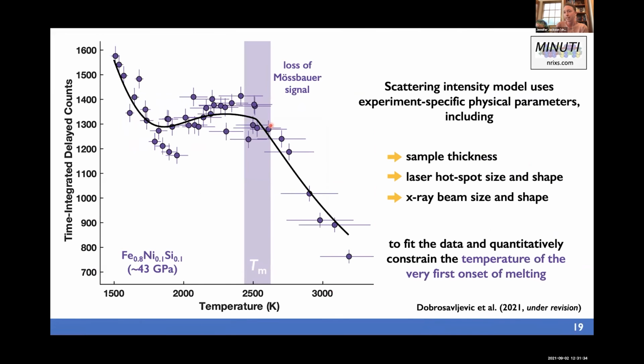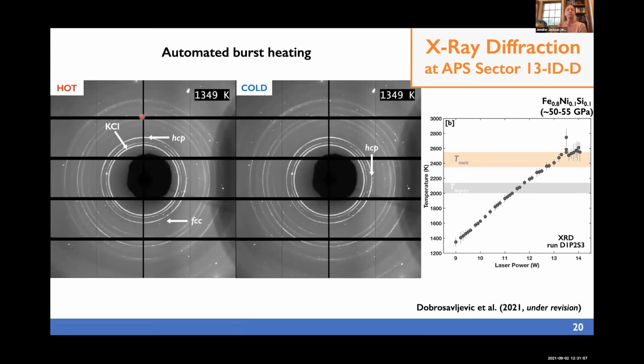The important thing to mention is that the determination of the melting point uses experiment-specific properties. So we use a physical model to describe the scattering process as well as a measured X-ray focus size, and that's incorporated in the fit to the data. We also use a sample cut from the same aliquot and the same loading conditions.